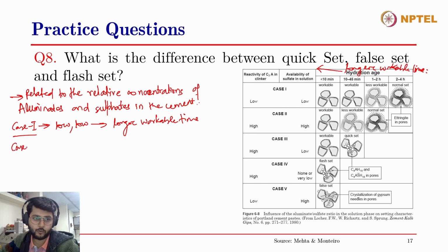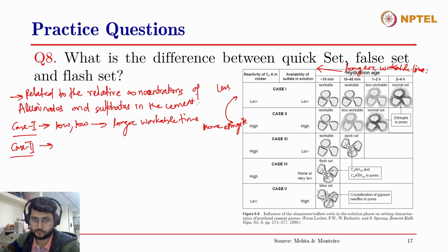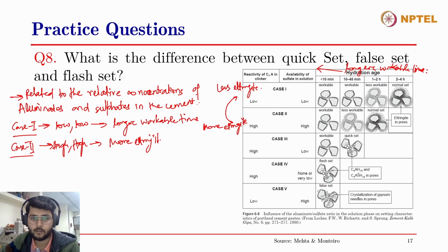Now coming to case 2, when the amount of C3A is high and the sulfate availability is also high. So meaning that there is enough sulfate and enough C3A in the system. So therefore more ettringite will be formed. This case 1 is less ettringite, right? Because the reactivity of C3A is low and the sulfate availability is also low. So in the second case, there will be more ettringite formed, high and high. Normal setting occurs, but it is a little faster.